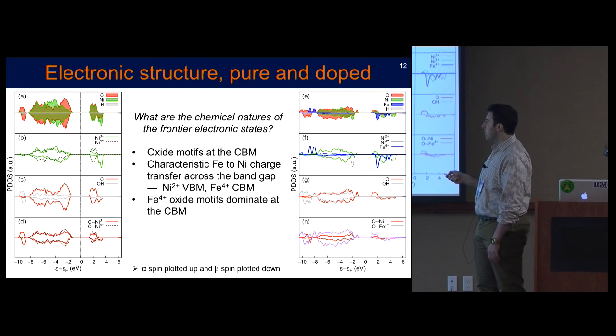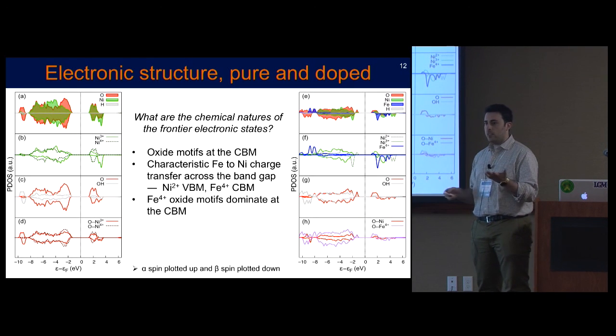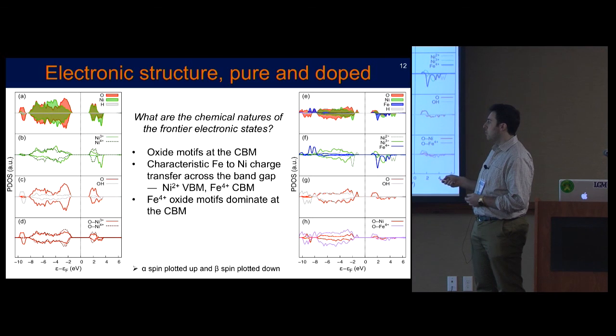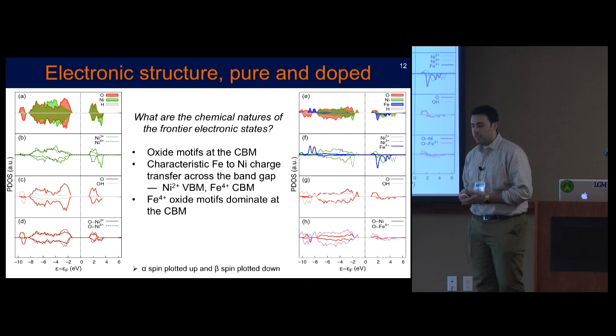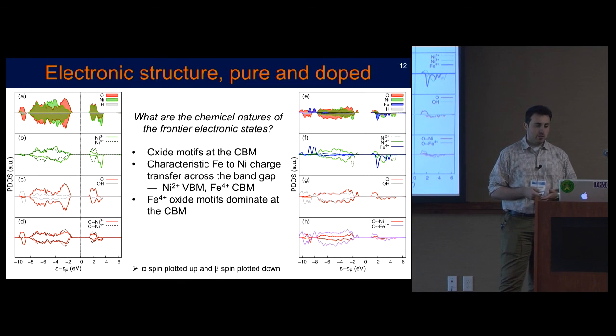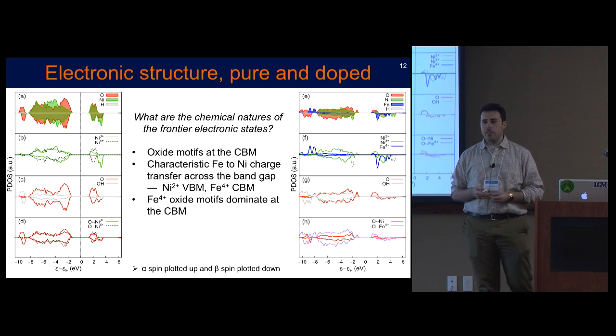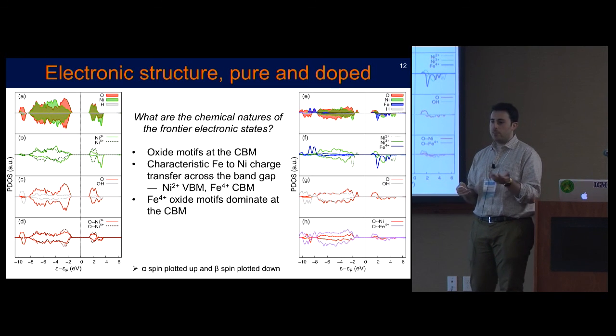So we can break this down in a number of ways. First, by metal oxidation states. So you can see nickel-3, nickel-4, where you can see in the valence band nickel-3 has that extra electron relative to nickel-4, so it shifts it a little bit higher up in the valence band. And then most importantly, if we keep an eye towards catalysis, you can see the oxygens or the oxide motifs, which have been deprotonated in the process of oxidizing the material, sit a little bit lower than their hydroxide counterparts in the conduction band. And we would expect that to be the case because those should be the more nucleophilic sites for an attack by hydroxide or water in the process of the oxygen evolution reaction.